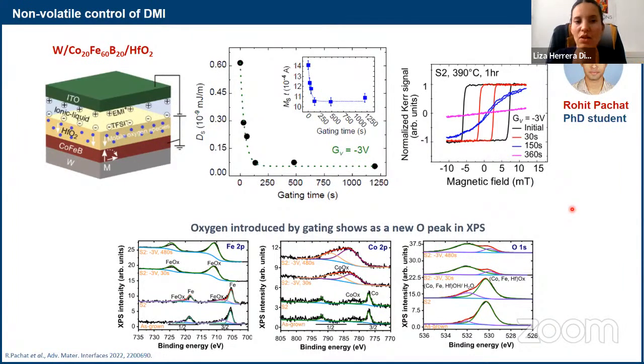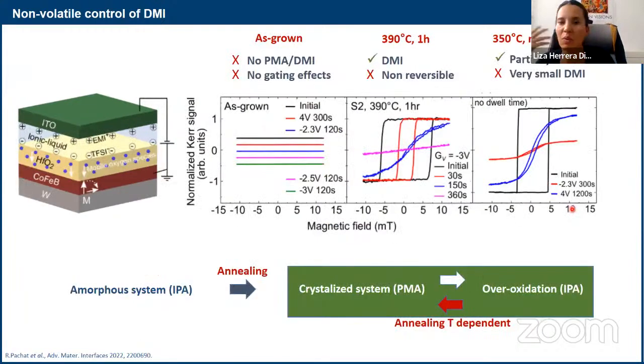So then if we're limited to ionic transport in the grain boundaries, that will limit the mobility a lot. We might put ions in, but it will be hard to get them out. We already have an asymmetry in the voltage that we have to apply to get ions in or to get them out, so this makes it very hard to recover the original state. So what we thought is, well, let's maybe anneal at a lower temperature so we can have a compromise between magneto-ionic performance and the magnetic properties, but we couldn't really succeed.